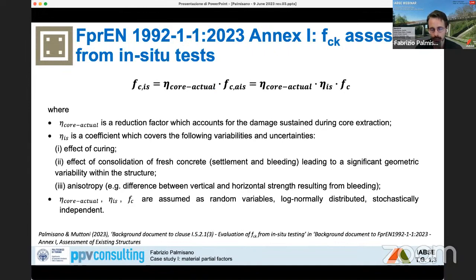I will show you the approach that we have used also in the case study that will be given in the forthcoming Annex I of the second generation Eurocode. This approach is based on the assumption that the in situ strength is the product of 3 parameters: the resistance of a cube specimen of concrete fc, a parameter eta core actual that is a reduction factor which accounts for the damage sustained during core extraction, and an in situ factor eta is which takes account of the effect of curing, effect of consolidation of fresh concrete, and anisotropy. These variables are assumed to be random variables, log normally distributed, and stochastically independent.